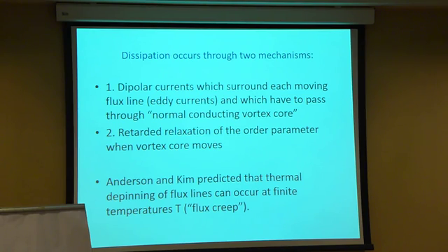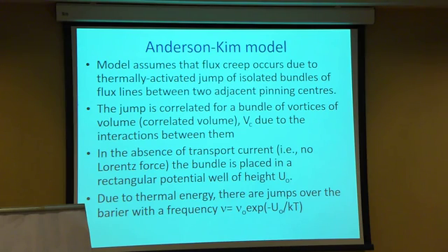So what we have there is a bundle of flux lines trapped in the potential well, but because we give them thermal energy, they can jump over the barrier. That jumping is the flux creep, and it is characterized by some sort of Arrhenius behavior because it depends on the temperature. This model assumes that flux creep occurs through thermally activated jumps of isolated bundles of flux lines between 2 adjacent pinning centers, and the jump is correlated for a bundle of vortices of volume Vc, the correlated volume, due to the interaction between the vortices.